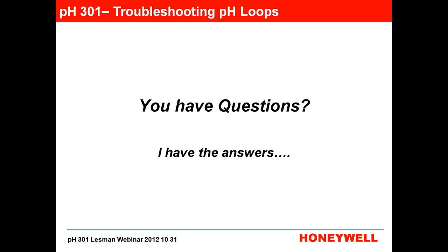So let's say you're at 35 degrees C and you're at 5 pH and you don't use temperature compensation, you're going to have an error of 0.06 pH units. If you're at 35 degrees C and you're at 2 pH, you're going to have an error of 0.15 pH units. Now let's say you're at 85 C and 2 pH, you are going to have an error of 0.9 pH units. So you always, always use temperature compensation. However, when you're doing a USP certified measurement, and our UDA 2182 has the USP programming in it, there's several ways that you measure and do your calculation.